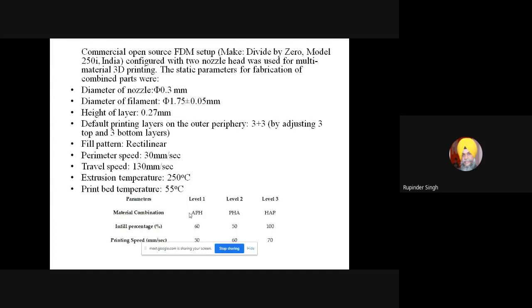So we selected some fixed parameters. One open source 3D printer has been used. The diameter of the nozzle we fixed, the diameter of the filament we fixed, then layer height, the number of layers that we are printing, their filling pattern, their printing speed, their travel speed, extrusion temperature. There are around 15 parameters that can be controlled on this type of commercial printer. Some of the parameters we kept fixed, and we try to explore the effect on the output property.